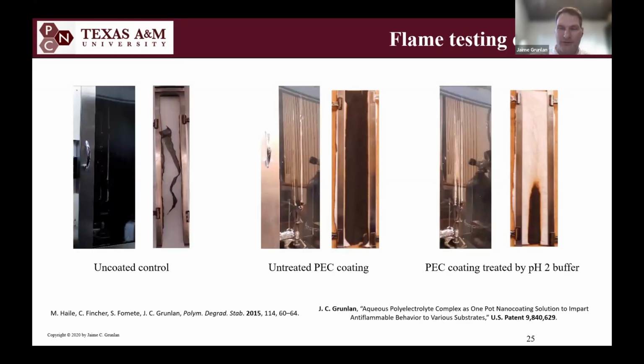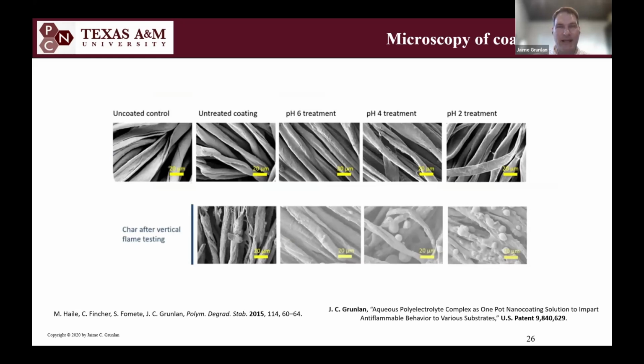And you could see this treatment, this polyelectrolyte treatment that we put on, was able to arrest that burning process, and we protected and we passed the vertical burn test. And as I changed the pH of that second step, that citrate buffer step, as I'm lowering the pH, I'm increasing the phosphate. It's actually altering the nitrogen to phosphorus ratio, and I'm getting a more favorable phosphate ratio, and I'm then getting a more favorable intumescent effect. And you can see the bottom set of images are post-burn, the top set of images are pre-burn. And by the way, you can see, much like layer by layer assembly, one of the big advantages of layer by layer assembly is that you get very conformal coatings. But this polyelectrolyte complexation that I did is also very conformal, much like the LBL process used to be.